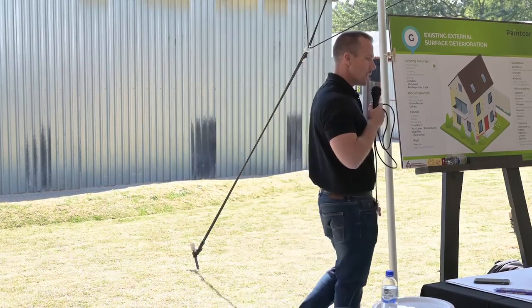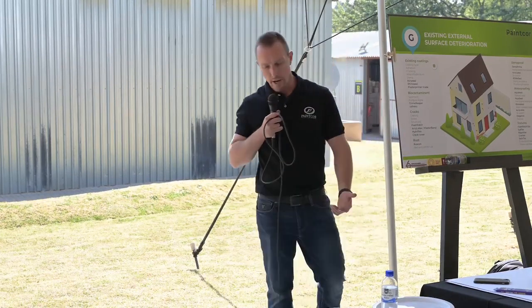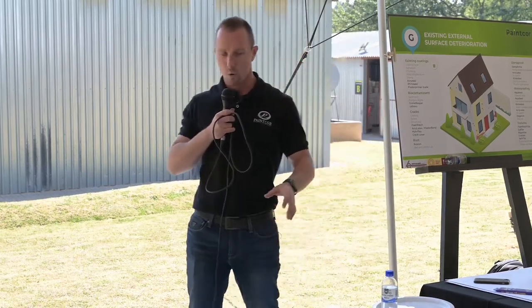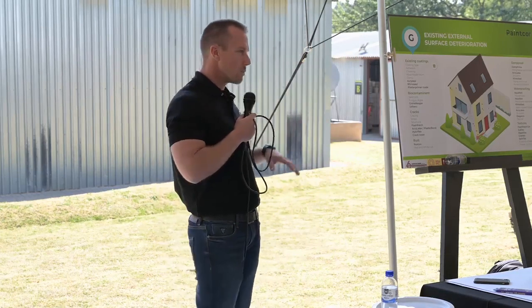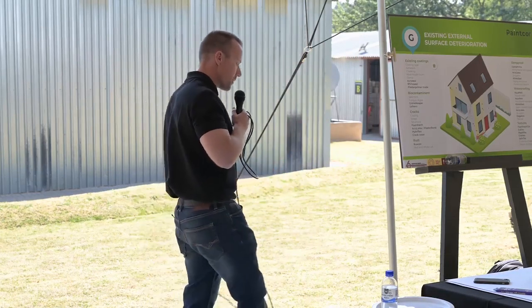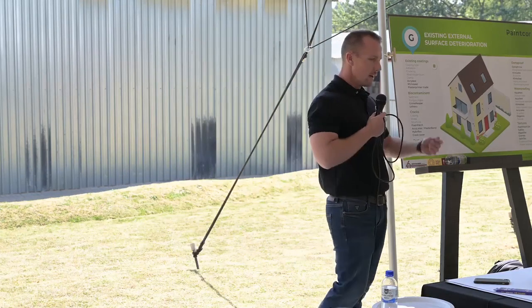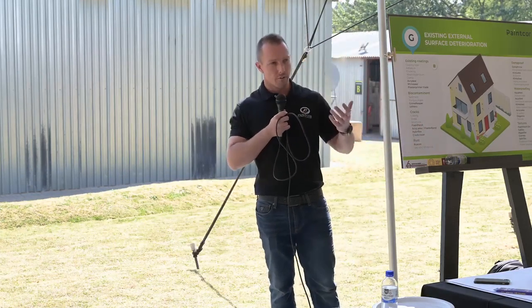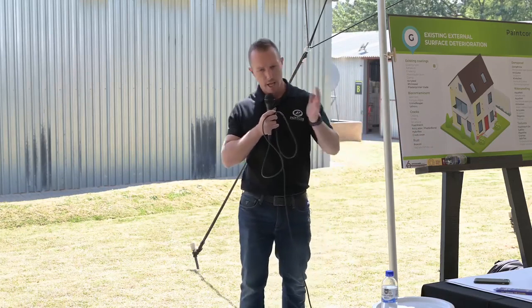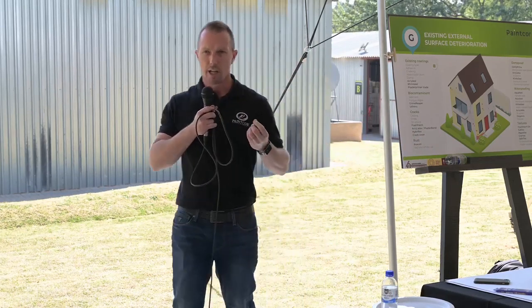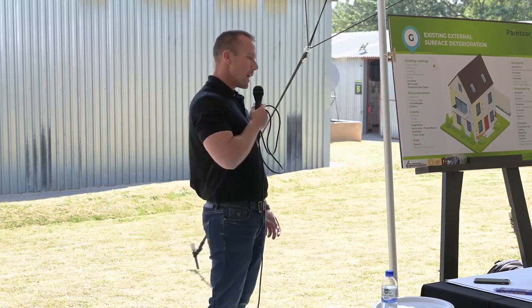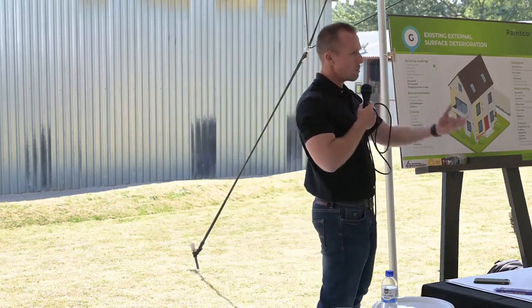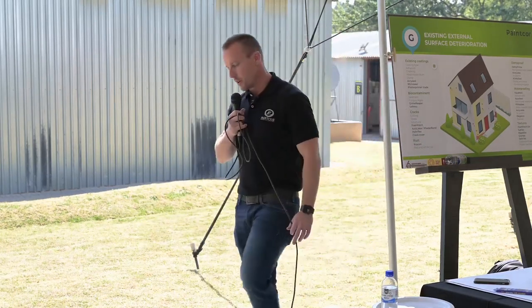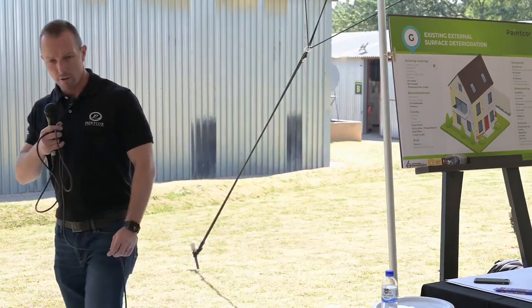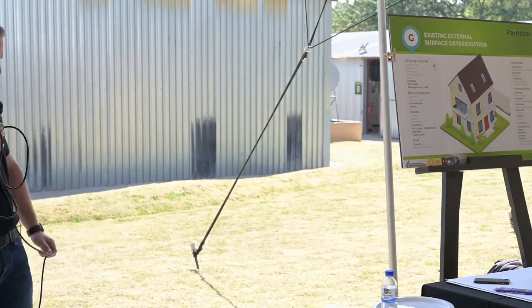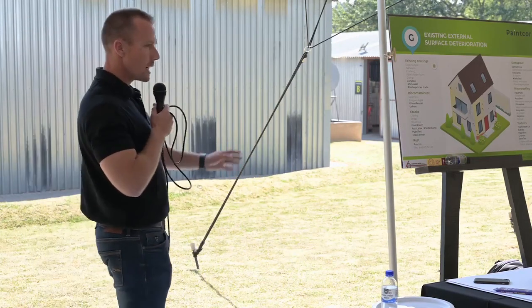If unfortunately the water ingress, the cracks, have allowed moisture or water to get in, not just behind your paint film, but to get into the plaster itself, you'll often see a more severe form of plaster cracking, even plaster delamination or starting to crumble and lose integrity. Now you've got a damp proofing issue that requires you to remove the plaster from the surface. So where this is required, you want to remove any loose, friable or otherwise deteriorated plaster. Then clean up the brickworks.